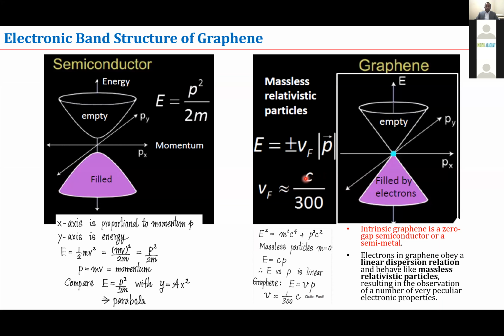Like if you consider, we know that the velocity of light is of the order of 10 to the 8 meters per second, divided by 300, this will be of the order of 10 to the 6 meters per second, the velocity of the electron in graphene. And because energy is linearly proportional, E equals v_F times p, you can expect a linear relationship between energy and momentum, and you do not have a gap here. Therefore, graphene is a zero gap semiconductor or a semi-metal.